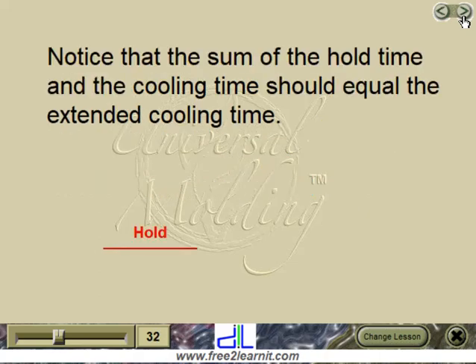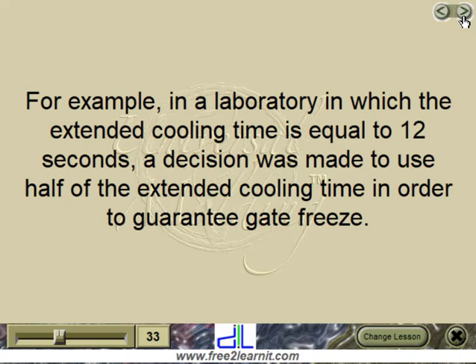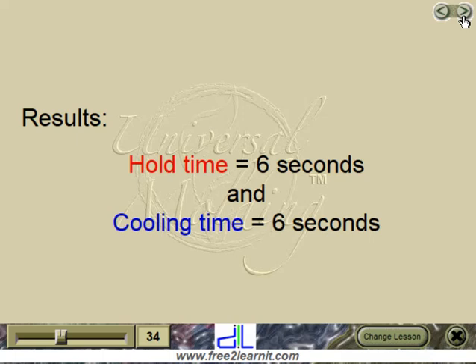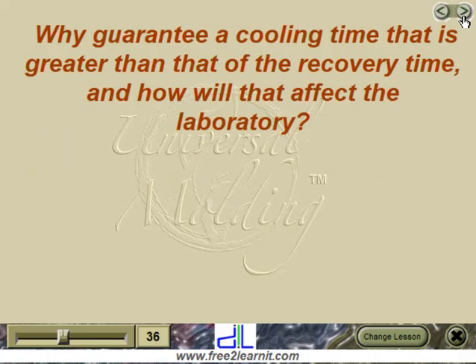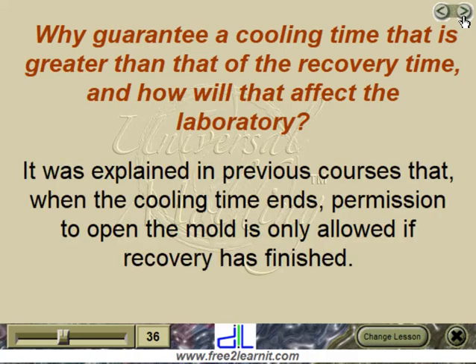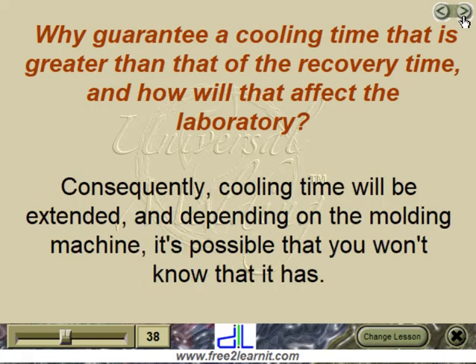The sum of the hold time and the cooling time should equal the extended cooling time. For example, in a laboratory where the extended cooling time equals 12 seconds, a decision was made to use half of the extended cooling time to guarantee gate freeze. It is important to guarantee a cooling time greater than the recovery time. When the cooling time ends, permission to open the mold is only allowed if recovery has finished — the mold will stay closed until recovery has ended, no matter whether the cooling time has finished. Consequently, cooling time will be extended, and depending on the molding machine, it is possible that you won't know that it has.